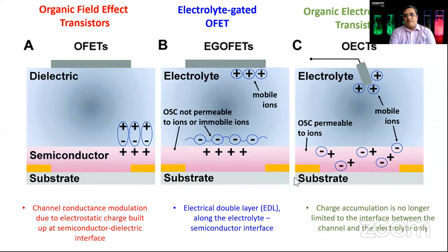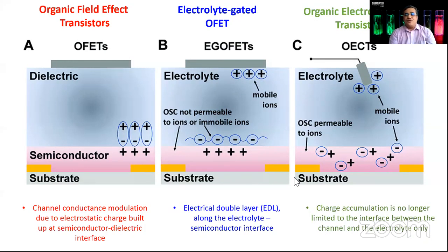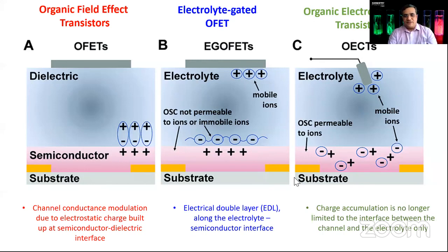In the organic electrochemical transistor, charge accumulation is not limited to the interface — it extends into the bulk. In EGOFET, the organic semiconductor has a nonpolar backbone or alkyl chain that does not allow ions to enter. Whereas in OECT, by introducing polar alkyl chains, mobile ions are permitted to go in and the material becomes permeable, giving both ionic and charge conductivity. This is why biosensor-type devices operate at very low voltage, which is one of the major requirements for bioelectronics.